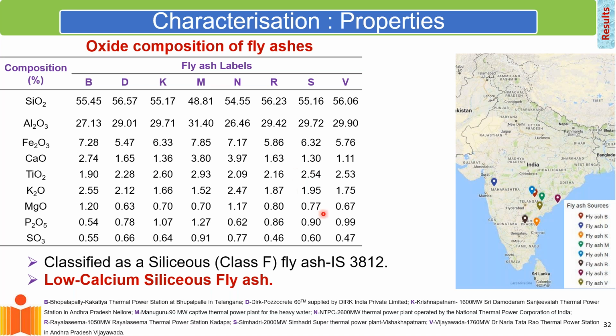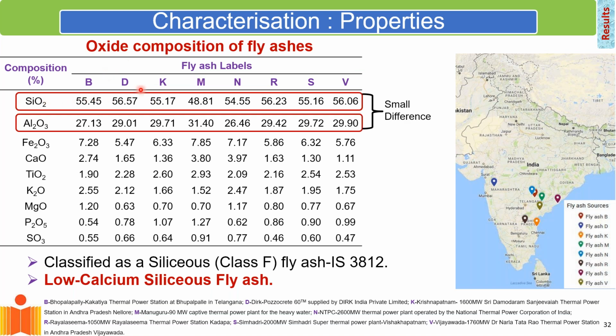And I just want to show you the kind of variability that we typically get in our fly ash. So we collected fly ash from different power plants around the country, and you do a typical oxide analysis. These are the oxides present in fly ash, and these are different sources from which we collected fly ash. You find that the primary oxides in fly ash, the silica and the alumina, are more or less similar within a small range of variation. But if you use these fly ashes in cement, you'd find that the results are night and day. You get a very large variation in compressive strength. So that means clearly that these numbers are not really telling us much if I just look at the oxide composition.